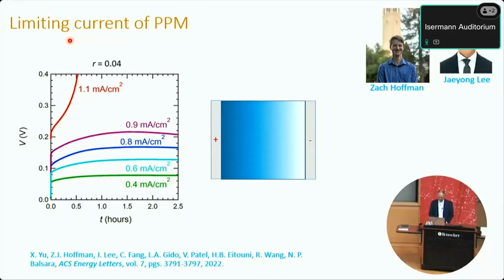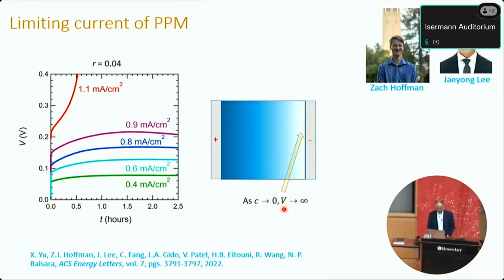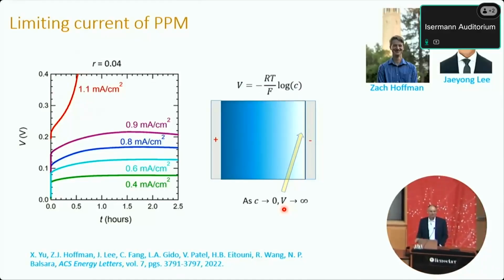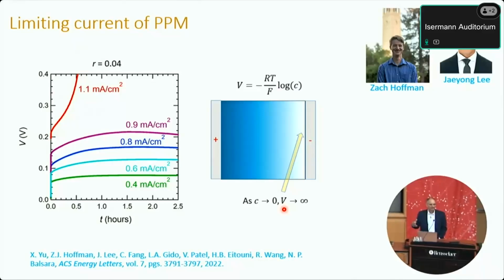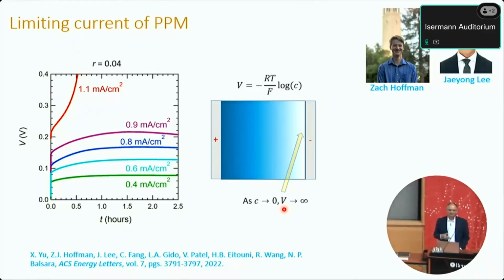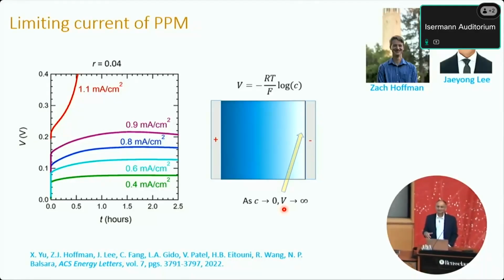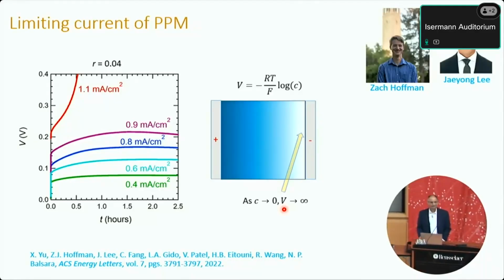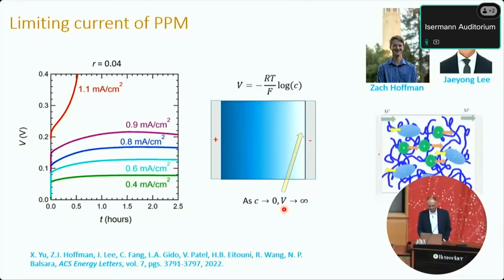This is a standard signature of reaching what is called the limiting current. Okay, so what is happening between 0.9 and 1.1, let's say at 1, is that the concentration near the negative electrode is approaching 0. And when that approaches 0, it's very easy to see that the voltage should be infinite. Because in the ideal case, the voltage is related to log of the concentration, and when something goes to 0, you get infinity. Okay. So this divergence is well recognized, not easy to measure, because lots of bad things happen on the way there if you're not careful about cell design, and that's really what we have done.